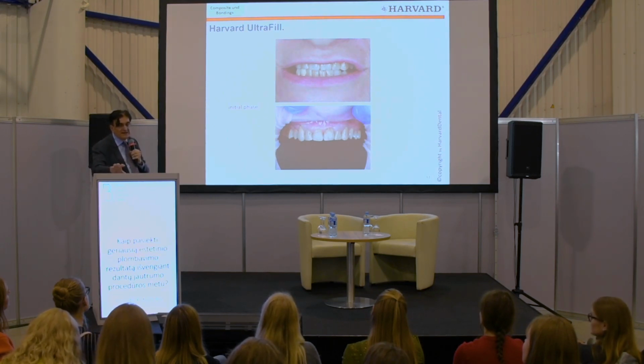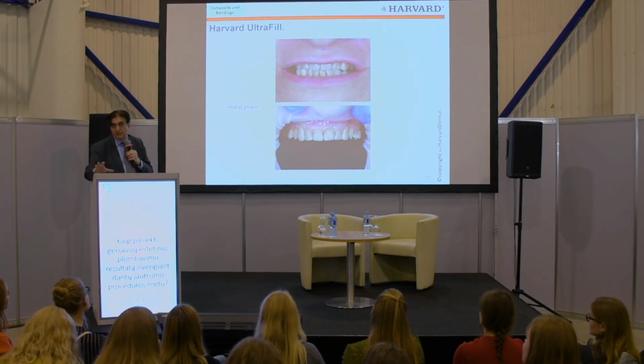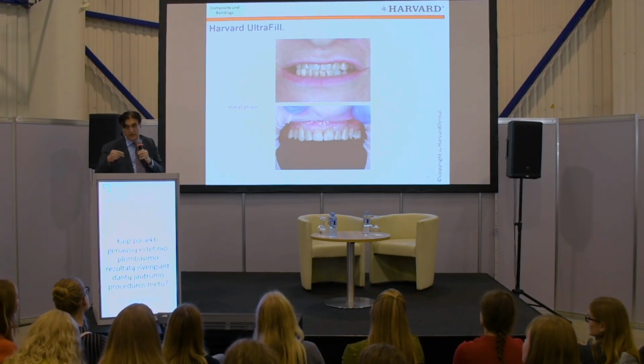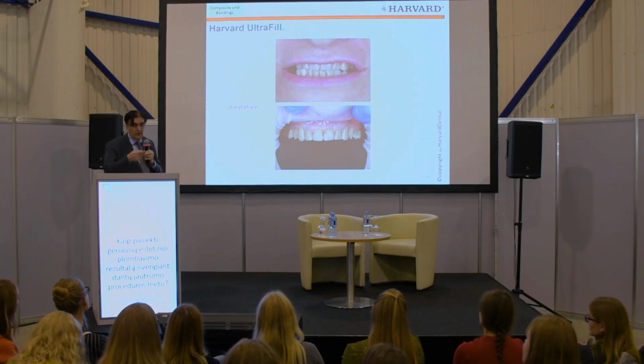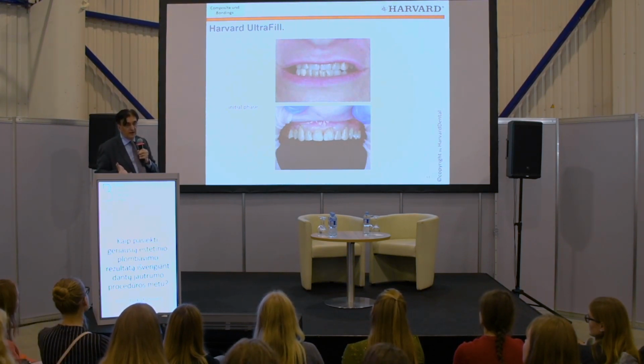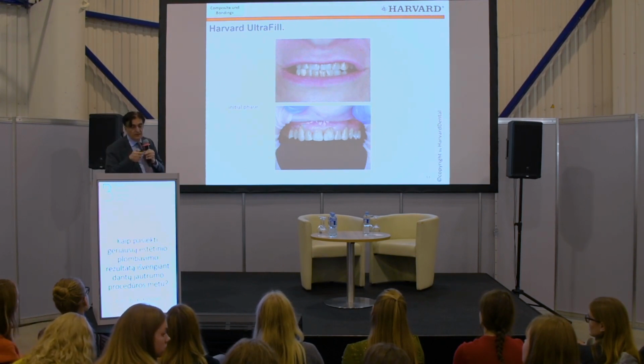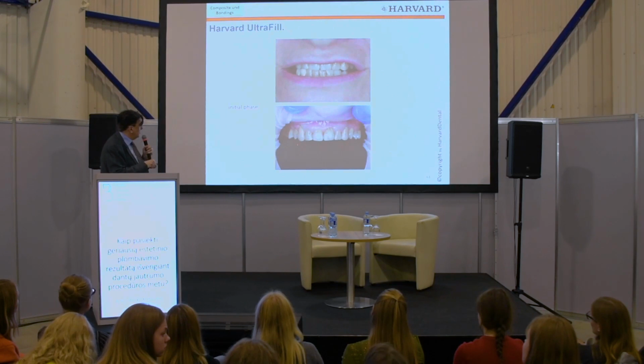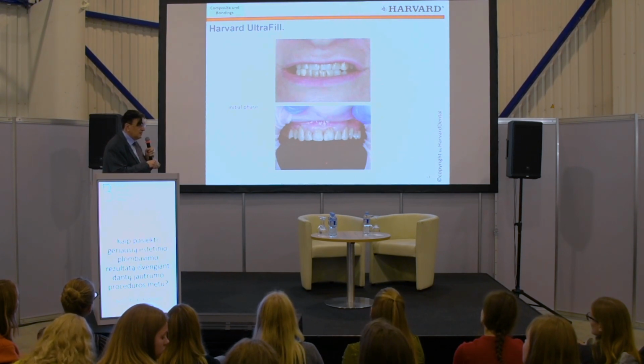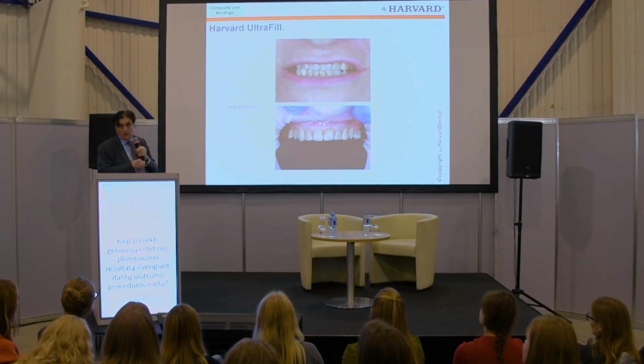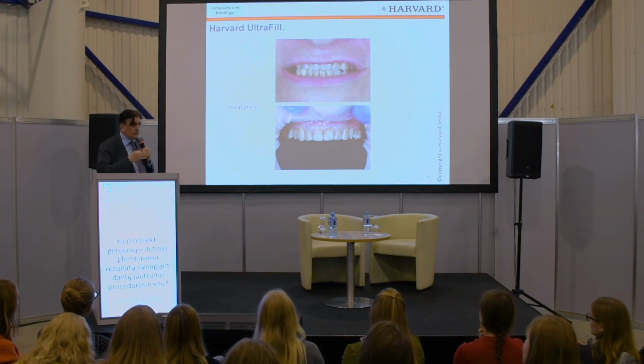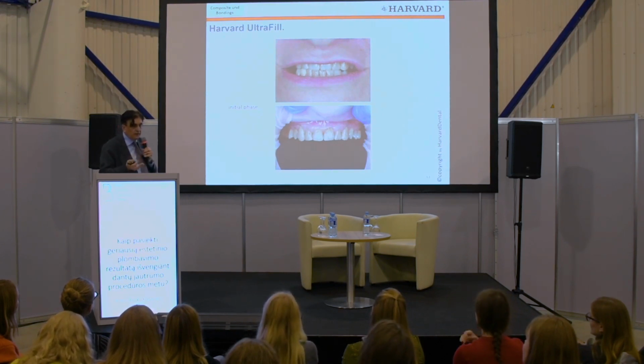No matter how splendid and how good the composite is, if you don't know how to use the adhesive, your filling is not going to last for a long period of time. And then later on, you will have those brownish lines between the tooth and the filling. This is not because the composite filling is not nice. No, this is because of you. You didn't know how to apply the right bonding agent.